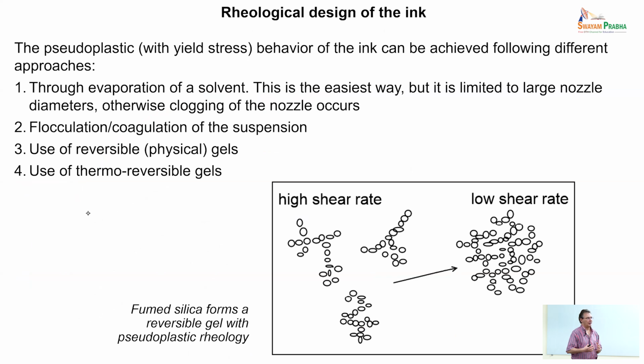And there are different ways in which you can do that. Of course, you need additives, and you can use fast evaporation of a solvent, but in this case, you might generate cracking. So you have to be careful. For FFF, let me just remind you, you do not have this issue. I mean, you still have the issue that you have a liquid layer that needs to be consolidated after being extruded. But in that case, the temperature does it for you. As soon as the temperature is reduced, the viscosity of the polymer increases a lot. Here, you have flow without temperature, so you need different ways of consolidating.